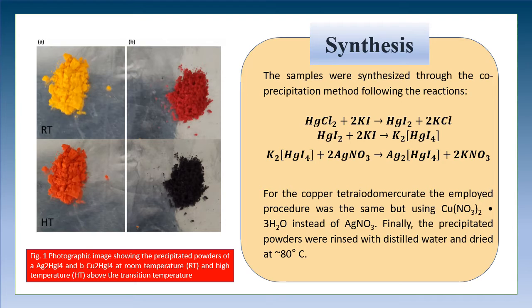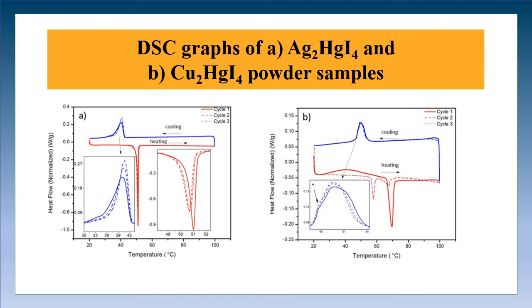The samples were synthesized by the co-precipitation method. In the DSC analysis results, the characteristics of the phase transition of the material are presented. Three cycles were performed to study the stability of the samples. For silver tetraiodomercurate, the thermochromic transition is observed with a minimum at 51 degrees Celsius, which is reversible with hysteresis when cooling. In the second and third cycles, a tiny shift of the transition peak was detected. The hysteresis is associated with the mechanical stress between the grain boundaries.